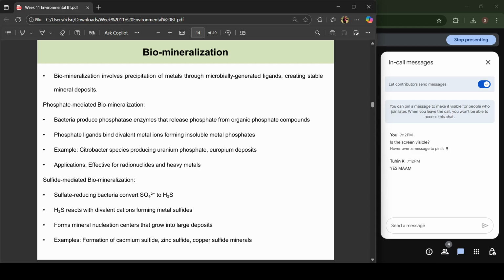There is one more mechanism, which is the sulfide mediated biomineralization, where sulfate reducing bacteria convert sulfate, SO4 2-, to hydrogen sulfide. And this hydrogen sulfide reacts with the divalent cations to form metal sulfide. So this forms mineral nucleation centers, and finally they grow into large deposits. So the examples of sulfide mediated biomineralization include the formation of cadmium sulfide, zinc sulfide, and copper sulfide minerals.